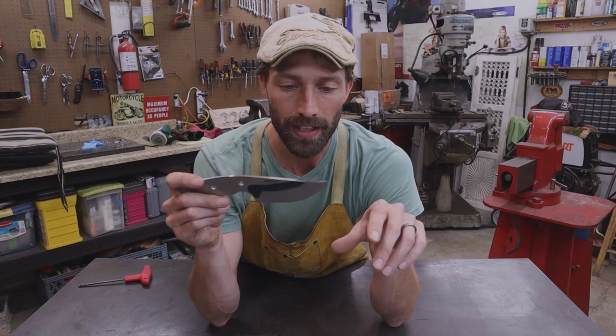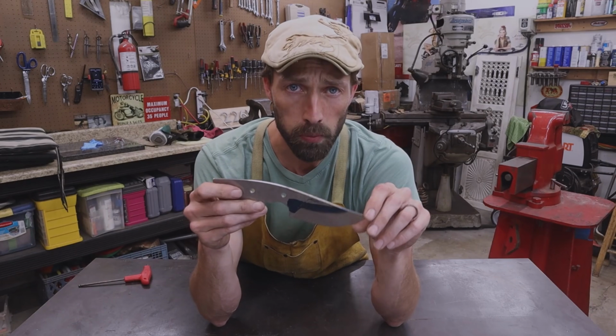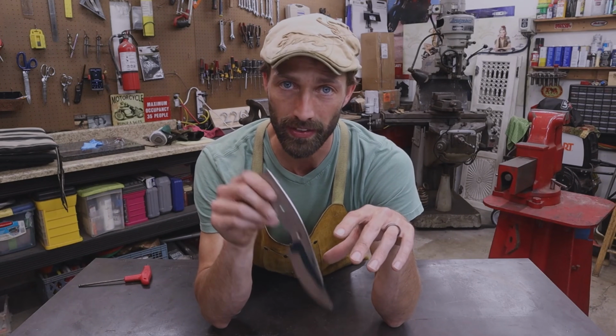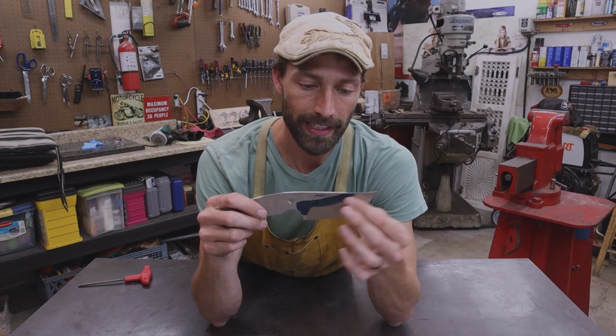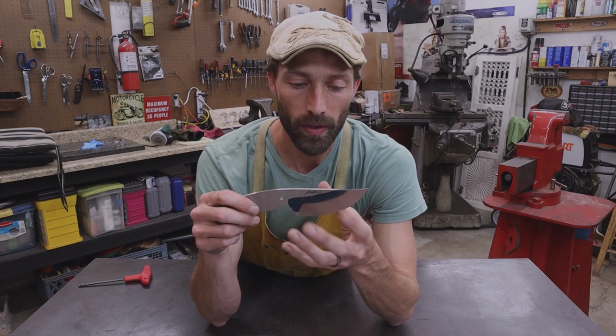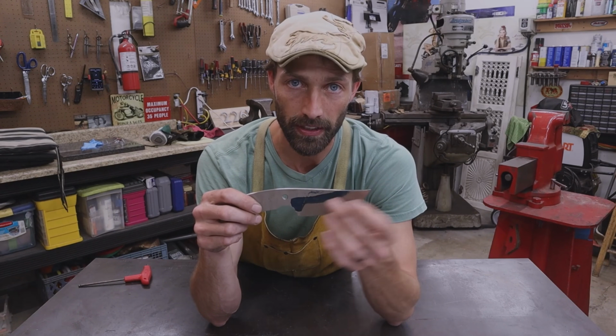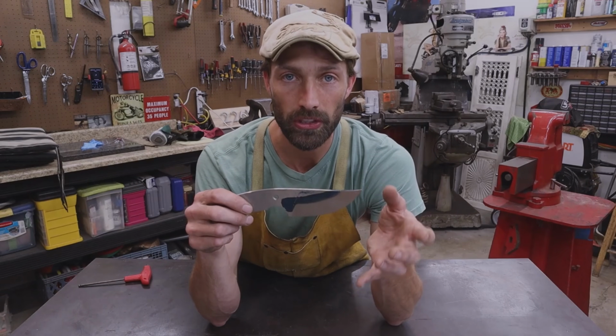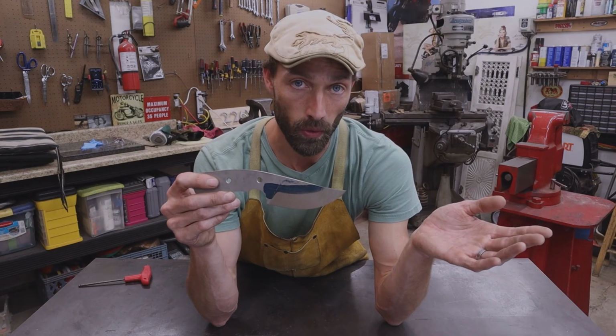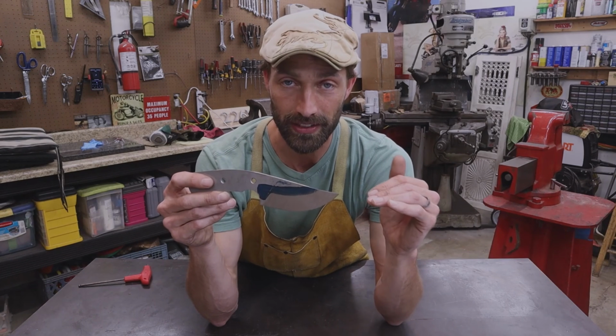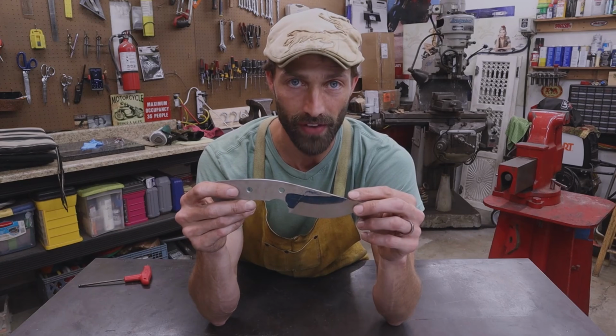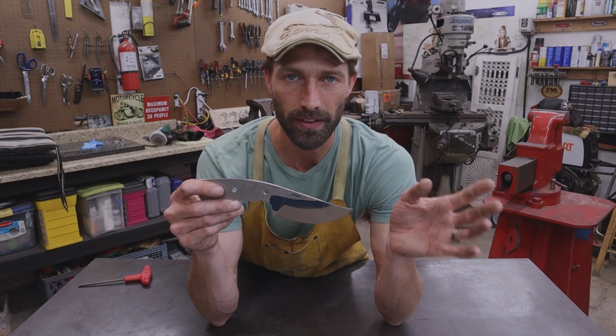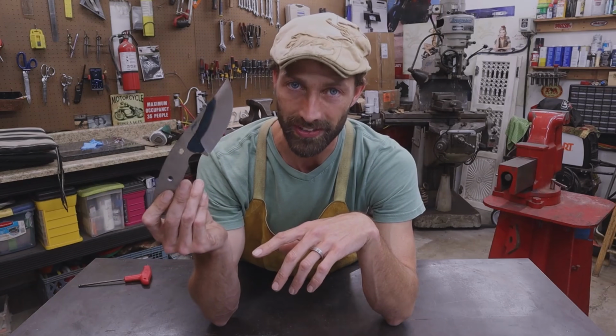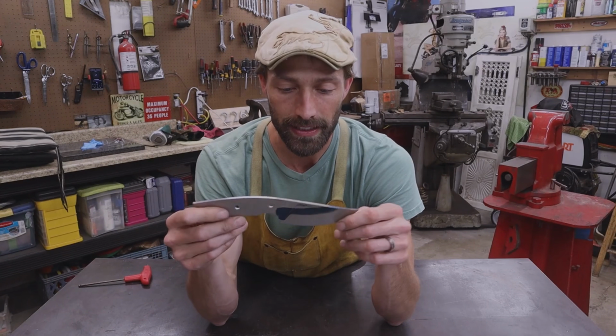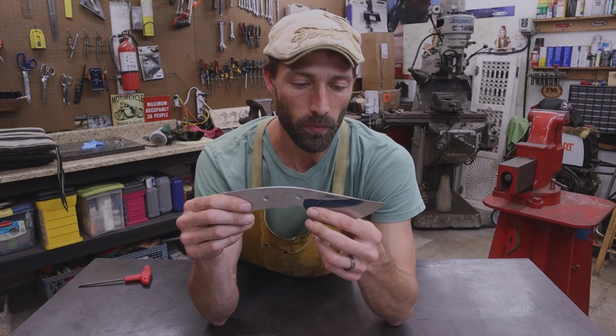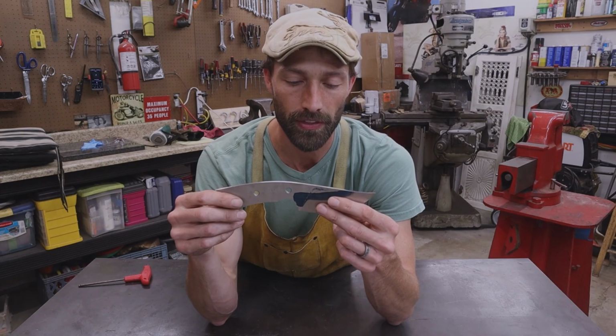And then when you put the knife in your quenchant oil, it's very important to agitate your knife very quickly, because what happens is a vapor jacket can form on this metal where it's not allowing the oil direct contact to the surface area, and it's not gonna quench the steel as fast as it should. So yes, we're gonna preheat the oil. That helps. That's thinning the viscosity of the oil so the oil can reach the surface faster. I know it seems completely counterintuitive to heat the oil to make this cool faster, but that is true. So we're going to heat the oil to thin the viscosity of the oil. That will help the oil reach the surface area of the steel faster.